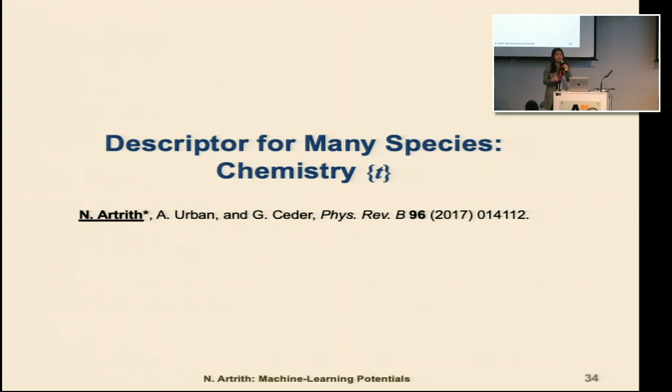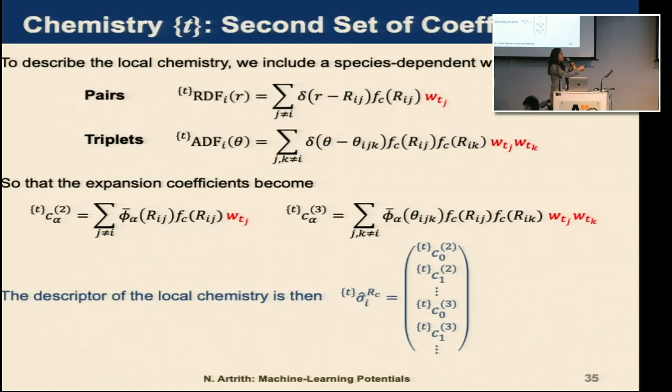So we also use a similar idea to the cluster expansion or Ising model, where they have many different chemical species or different sites. They use spin up and spin down. In this case, we use a similar idea by having different chemical species represented by just simple different numbers.